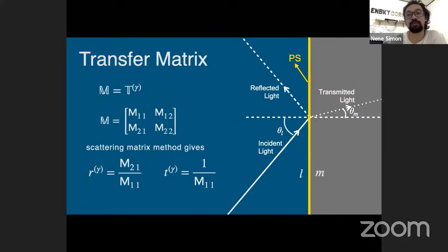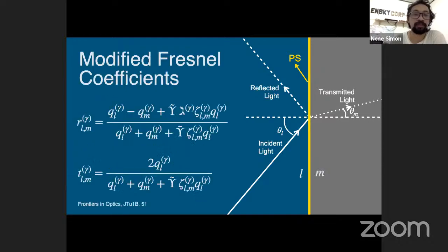So the standard scattering matrix approach gives us expressions for the reflection and transmission coefficients in terms of the elements of the effective transfer matrix. In this case, the effective transfer matrix is just equal to the transmission matrix. So to solve for the reflection coefficient, we have M21 over M11, while the transmission coefficient is equal to 1 over M11. From there, we derive the modified reflection coefficient for a perfect sheet sandwiched by two bulk media. To retrieve the original Fresnel coefficients, we can simply zero out the upsilon tilde terms here and here. And this one also. And that's elegant, isn't it?